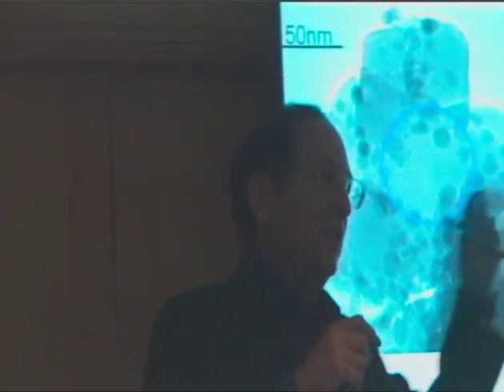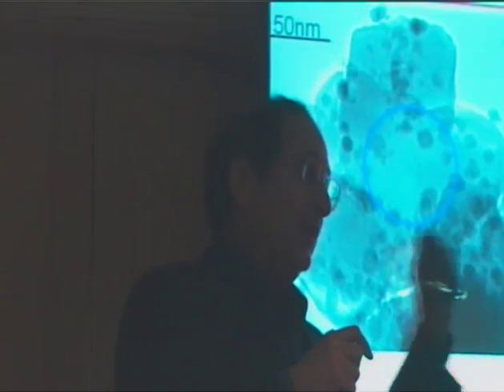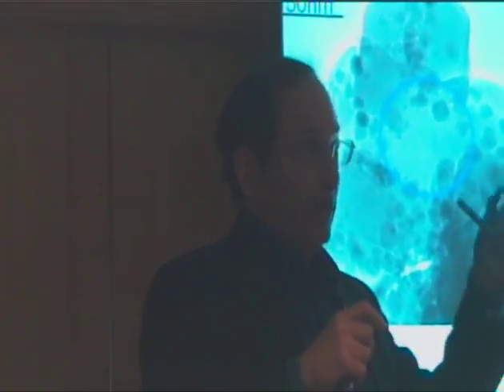So what she did to really make this an interesting study, she constructed a little fixed bed reactor, a very small one, where she could put the holey carbon grid underneath the bed, at the exit of the bed, and so adjusting how much catalyst she had there and what the flow rate was, knew what the effective conversion would be. So she could run low conversion, high conversion, and then she was able to take the holey carbon grid, transfer it inertly back into her microscope, and look at actually the same area of the catalyst and the same cobalt crystallites that were there before the treatment.